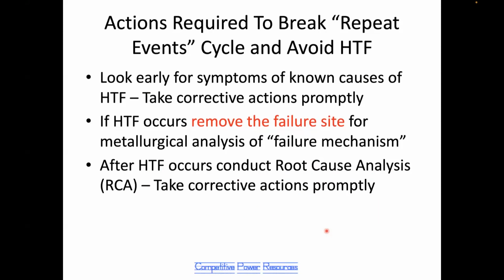If tube failure occurs, it's very important to physically remove the failure site so that you can send it to a metallurgical lab to determine the failure mechanism. After the tube failure occurs, a root cause assessment should be executed to identify what in the operation, design, or maintenance activities caused this tube failure or contributed to it, and then take corrective actions promptly.